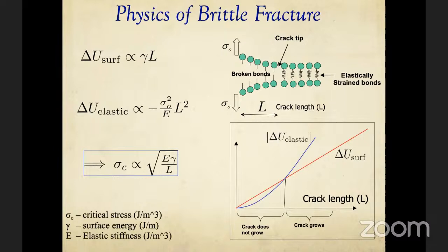And so Griffith worked it all out, and he found that there was a critical stress that depended only on the material properties. E is the elastic constant, gamma is the surface energy. These are properties of the material, that's all we need to know. Length is just how long this crack is. And he said, anytime a stress at the crack tip exceeds this number, that part will fail.